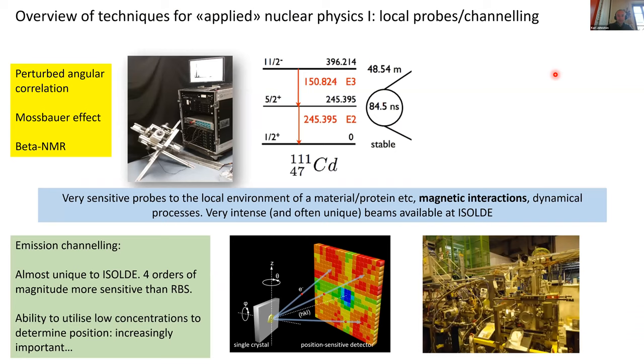Here's an overview of some techniques and what they look like in the lab. The Mössbauer effect you saw, and here is its cousin — perturbed angular correlation. Here you see a similar sort of decay scheme going through a double gamma cascade, with an intermediary state with a half-life of about 84 nanoseconds which is sensitive to the local environment. Here's a modern digitized PAC spectrometer where a small sample is held inside six different detectors. These techniques are very sensitive to the local environment of the material and especially magnetic interactions.